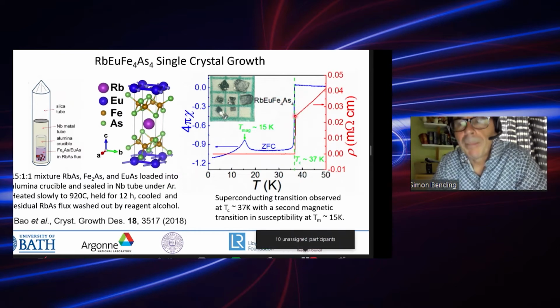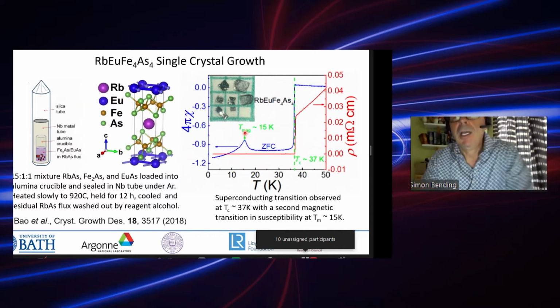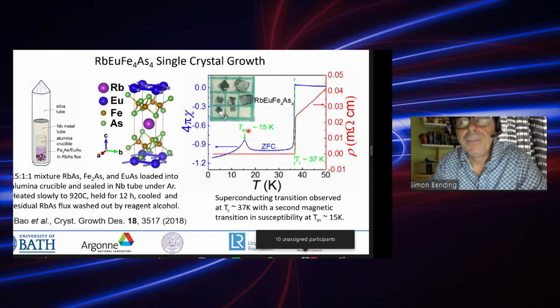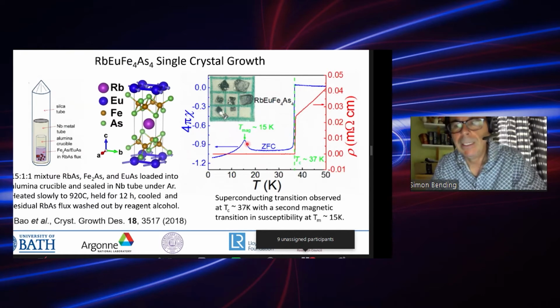And we see a very sharp resistive transition to a zero resistance state at about 37 Kelvin. And we can also, in parallel, study the susceptibility, the blue curve here, which shows this sharp drop as the system turns diamagnetic below Tc. But interestingly, it also shows this second cusp here, which is the signature of an ordered, essentially a 2D BKT type magnetic transition, which we can see now very clearly in the susceptibility, which is nice. And that occurs at around 15 Kelvin.